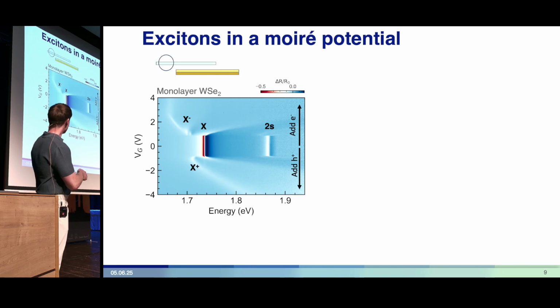This is the reflection contrast spectrum of a monolayer of WSe2. This is the part of the device where a monolayer overhangs the bilayer electron system, and we don't have any contributions from the Moiré layer.